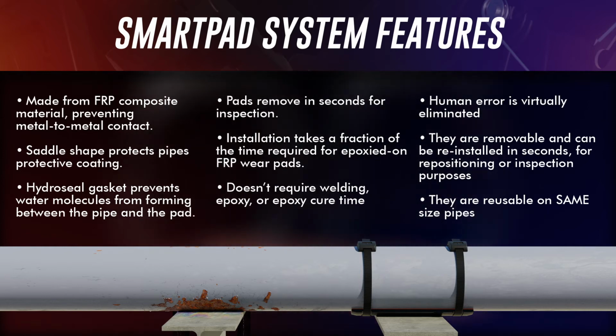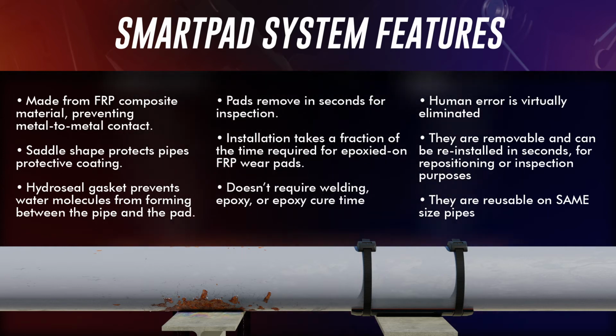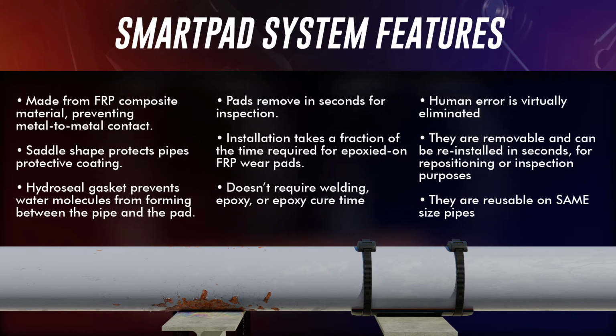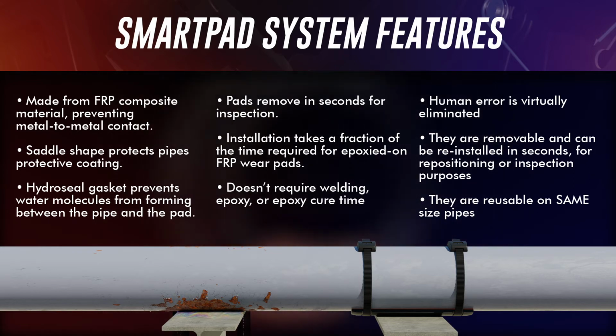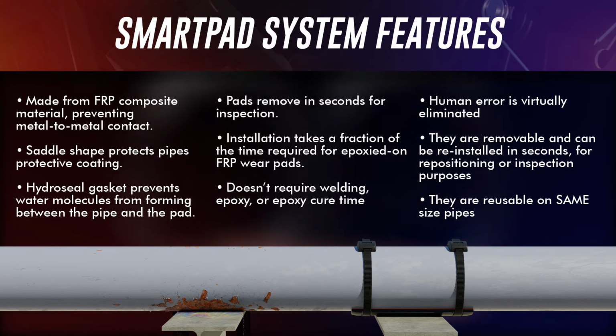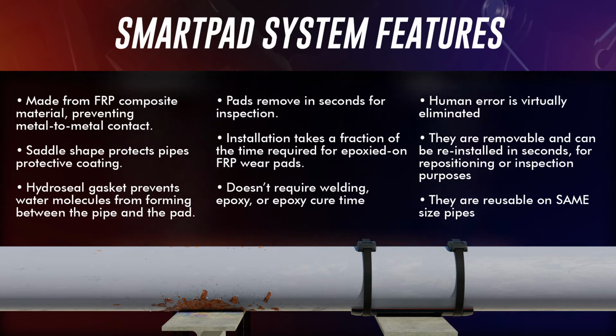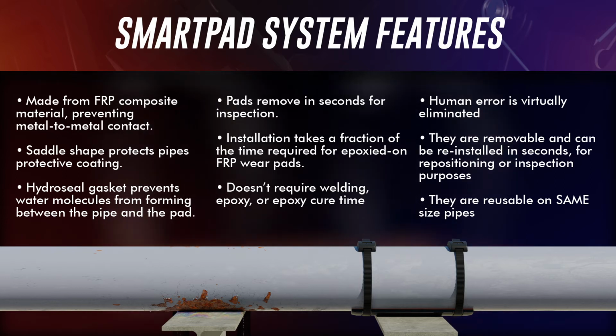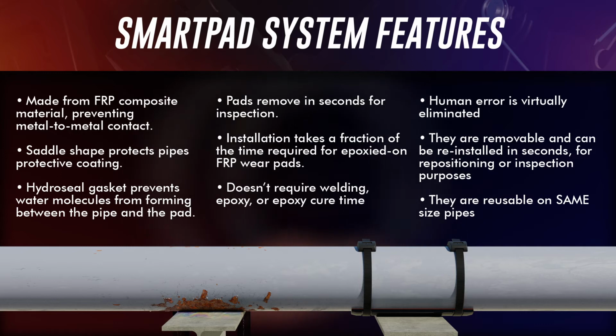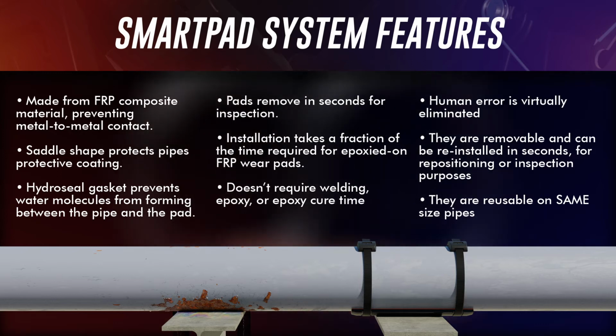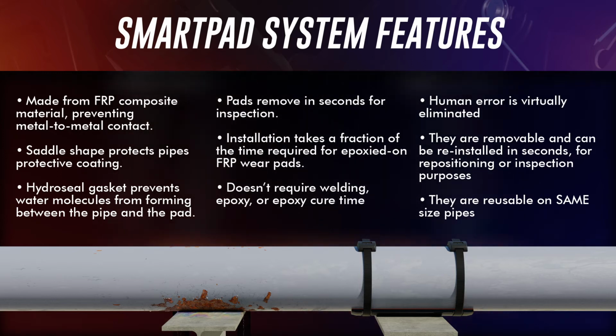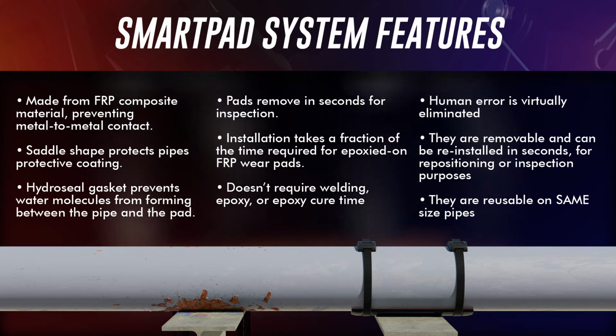The SmartPad installation takes a fraction of the time required for epoxied-on FRP wear pads. They do not require welding, epoxy, or epoxy cure time. Human error is virtually eliminated. Installer experience is not critical. They are removable and can be reinstalled in seconds for repositioning or inspection purposes.